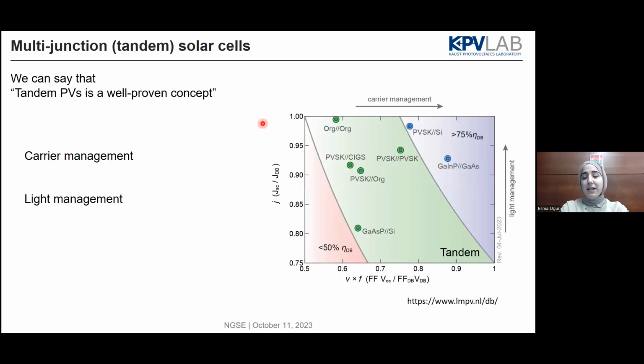And I like these AMOLF graphs, which show how you can really push the limit of these different technologies towards the detailed balance limit. Basically, it comes down to carrier management and also light management. You can see that perovskite-silicon tandems and perovskite-organic tandems are just lying around here. With the perovskite-silicon tandem, last year was an interesting year, as the efficiency is now more than 33%.